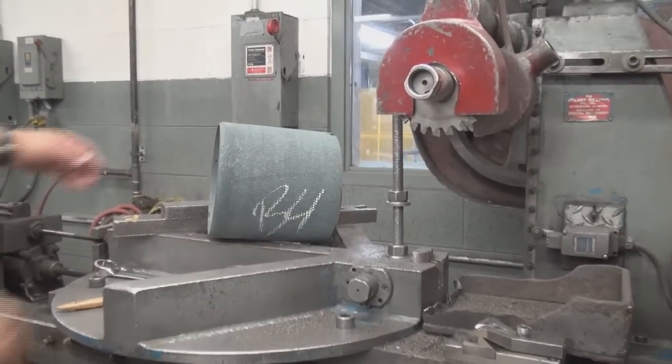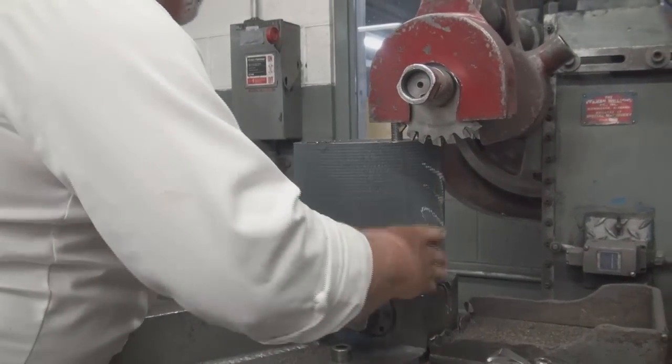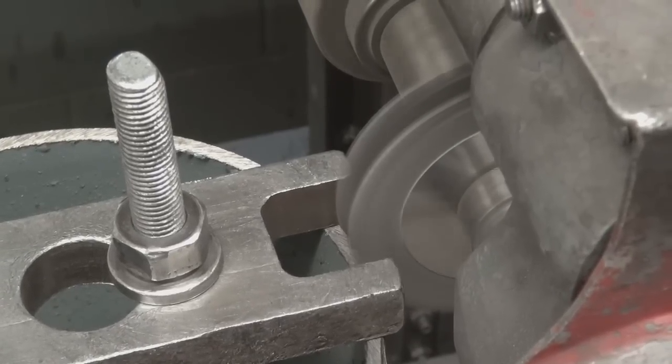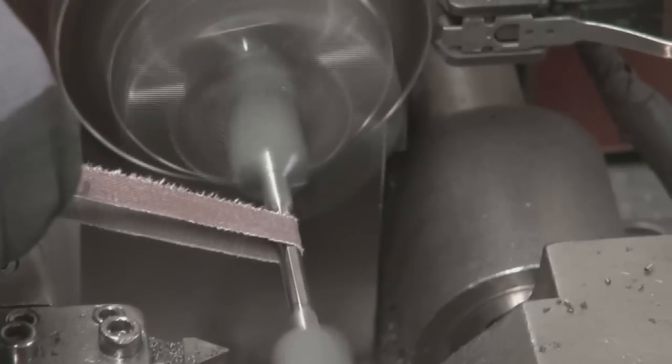Samples of pipe are also taken at specific intervals to determine mechanical properties such as tensile strength, yield strength, elongation, and impact strength. The tensile test begins with a piece of pipe being trimmed off on the plant floor and being sent to the lab where a smaller sample bar is cut out. The bar is placed in a lathe and machined down to a required diameter.